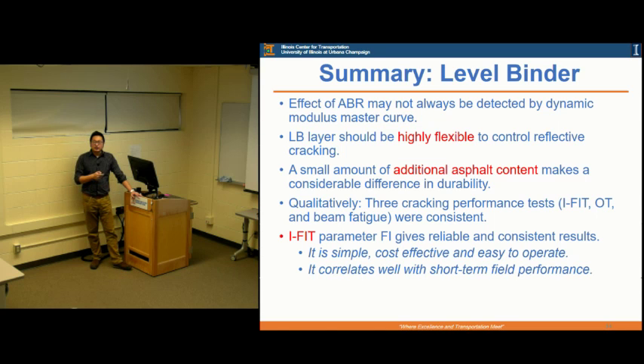You can see that in our case, even though it's been less than 1 or 2 years, we see cracking here, which means that if you put a lot of RAP and RAS in your level binder course, you may end up with a lot of cracking. Also, you can see that if you get just a little bit more asphalt content, not a lot, you can improve the durability and the fatigue resistance.